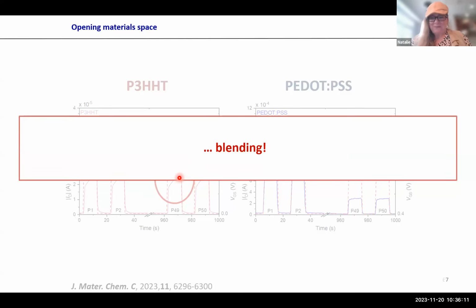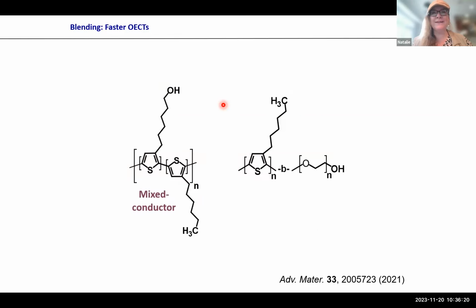So being sort of a one-trick pony, we went on and said, well, let's blend again. This time we were a bit more creative maybe than just using polyethylene oxide. Clearly that still needs to be judged. So we used our P3HHT, P3HHTT with some alcohol groups every now and then. And as an additive, we didn't use a commodity polymer. We used actually a block copolymer. That's why we have here the B for block of P3HT and ethylene glycol block.